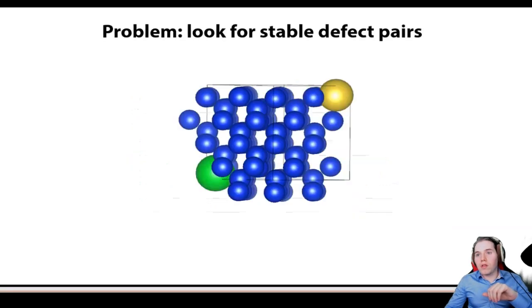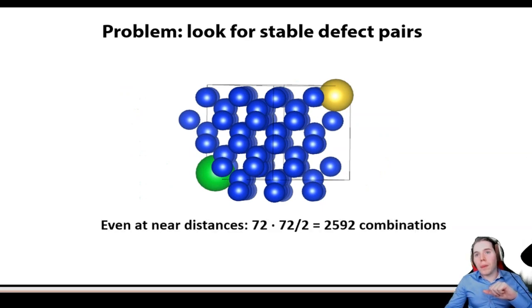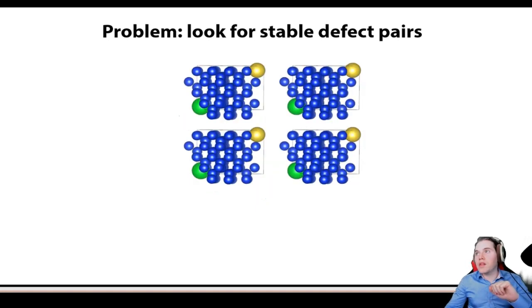And so we try this for a more complex situation where we actually replace two atoms. Note that if these atoms are in these specific positions, you already have around 2,600 combinations, which gets a lot worse if you would, for instance, replace different atoms within the box, as then you could have many different types of combinations. But we are going to stick to the ones in these positions and try to find the ones with the lowest energy using this kind of active learning. What's also important to realize again is that we repeat these boxes. So in actuality, these two atoms are next to each other, which of course allows them to interact in very specific ways.